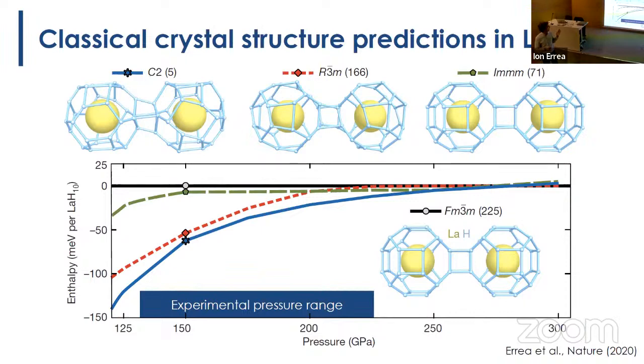So here, one approach to discover this material was crystal structure prediction. What is crystal structure prediction? People take a stoichiometry and try to look for the compounds at a given pressure that have the lowest enthalpy. This was very developed about 20 years ago, and it has been crucial to discover these compounds. But these calculations are classical, so they work in the Born-Oppenheimer energy surface.